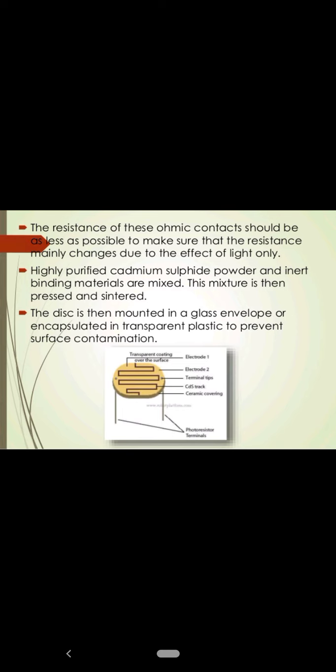Highly purified cadmium sulfide powder and inert binding materials are mixed. This mixture is then pressed and sintered. The disc is then mounted in a glass envelope or encapsulated in transparent plastic to prevent surface contamination. So this is the diagram of a light dependent resistor.